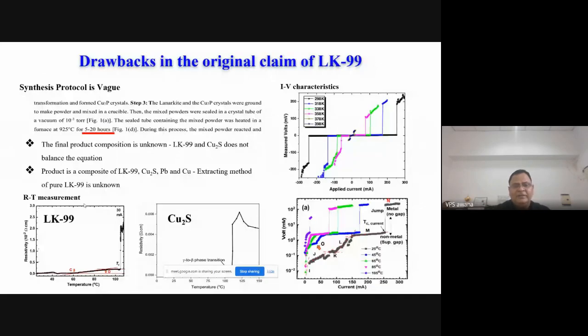Then I would like to say, because when we failed the second time, I thought let me see very closely what are the things with the LK-99. One problem with the LK-99 which I could see is that their measured volts and applied current in the IV characteristics very well show that it's a superconductor. It looks like, in fact it is. But when I did see, we are talking about 100 millivolts, 200 millivolts and coming to zero. In fact, the log of the same picture shows it was never R equal to 0. If you see in the lower panel, R equal to 0 stage is not there.